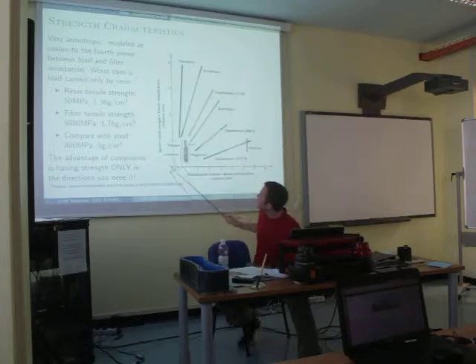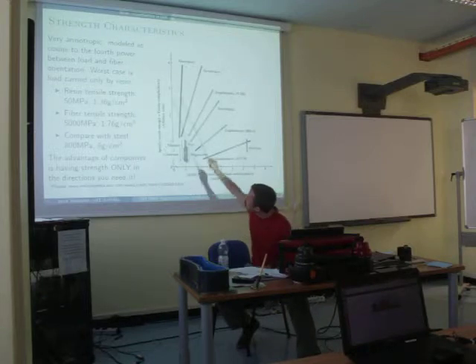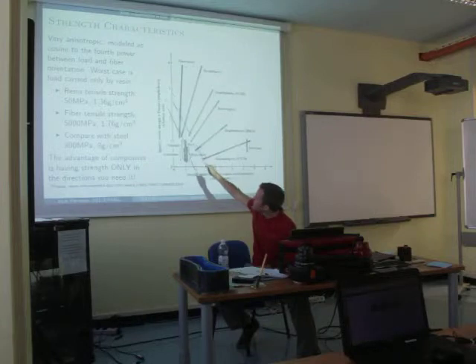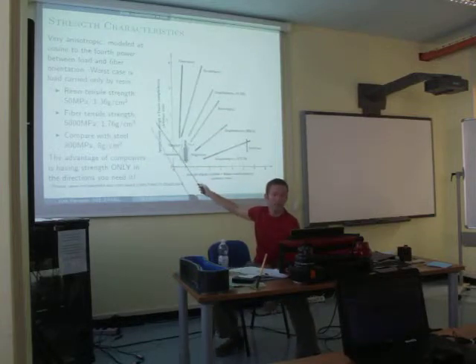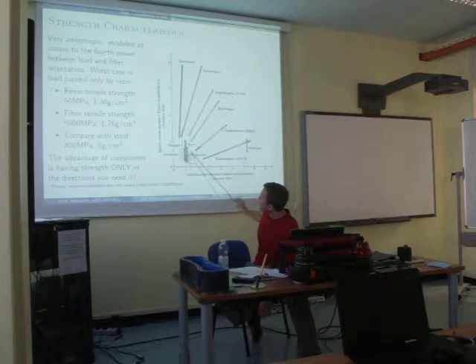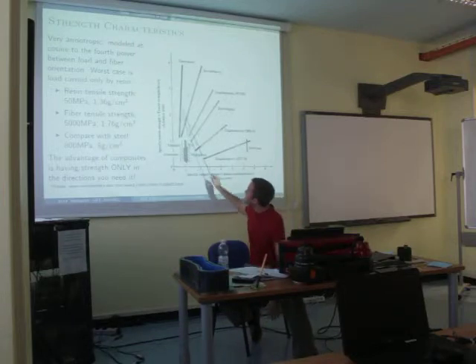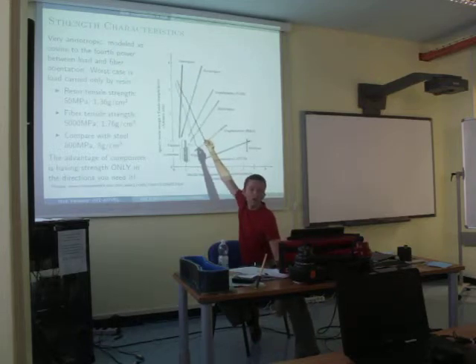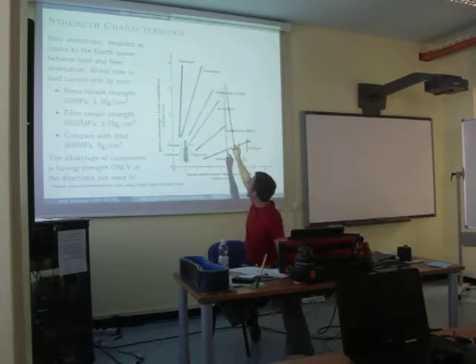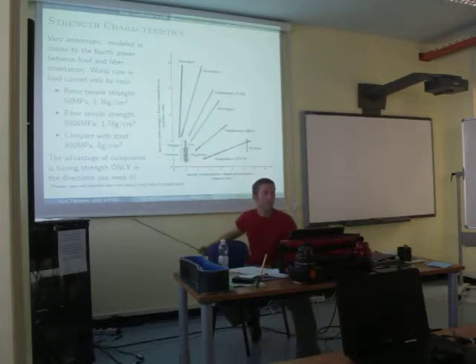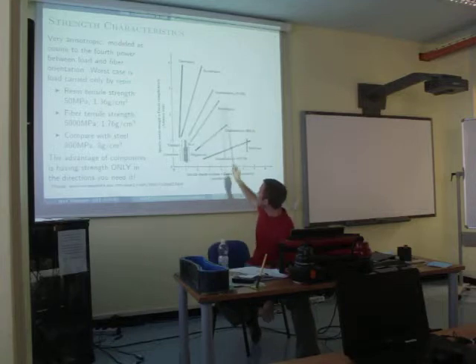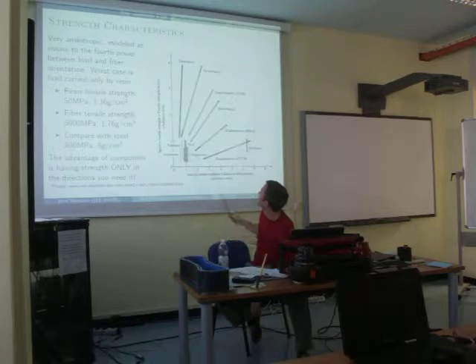So the specific strength here, for example, these are some elastic moduluses and the specific tensile strength, so the strength divided by the density. Here are the metals, aluminum, titanium, steel, magnesium. You can see that glass can actually be much stronger, fiberglass, and epoxy and graphite can be pretty strong, but you can actually have some fiberglasses that are stronger than graphite or carbon fiber. By the way, graphite and carbon fiber are the same thing, they're just named differently for historical reasons.